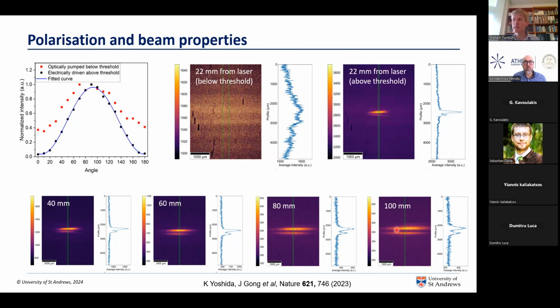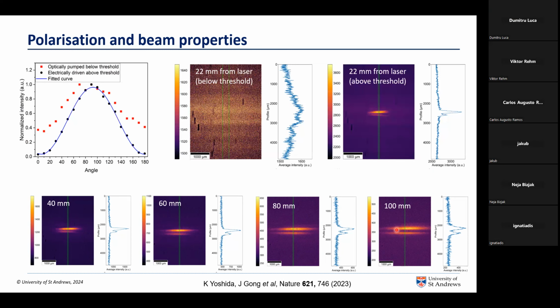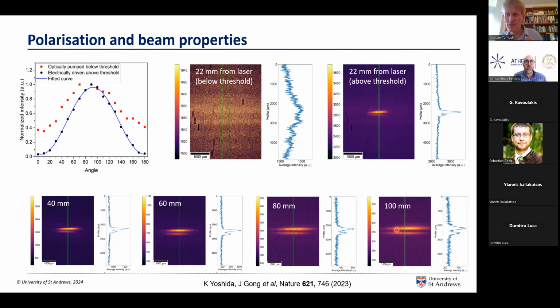We find also that this device will last for of the order 10 to the power 5 pulses before the OLED decreases in power by about 5 to 10%, and the laser threshold increases by a similar amount, and then we drop just below threshold. But there's lots of scope to extend that into many millions of pulses and beyond.